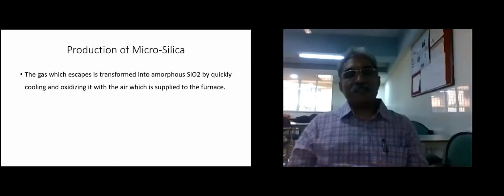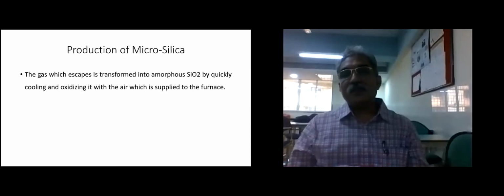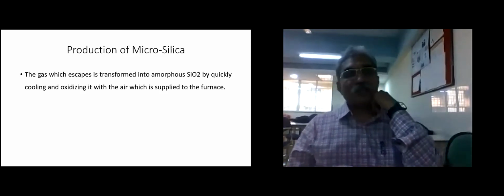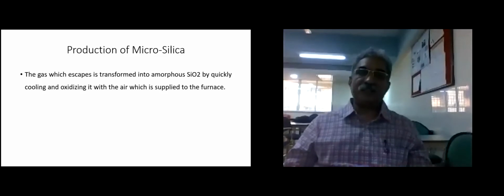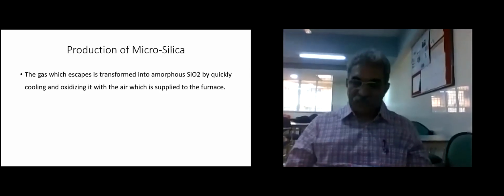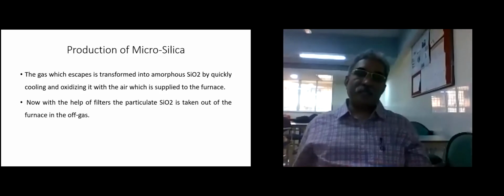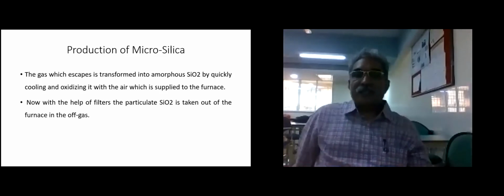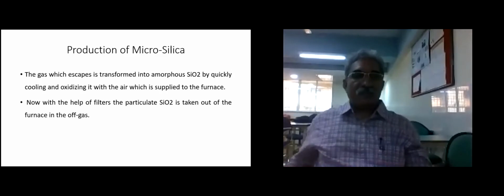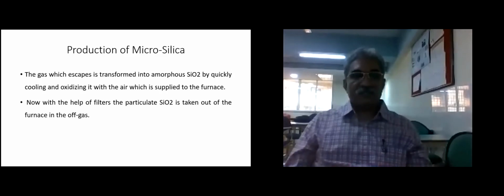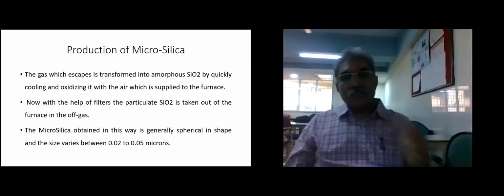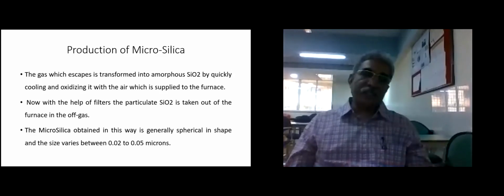The gas which escapes is transformed into amorphous SiO2 by quickly cooling and oxidizing it with the air which is supplied to the furnace. Now, with the help of filters, the particulate SiO2 is taken out of the furnace in the off gas. The microsilica obtained in this way is generally spherical in shape, and the size varies between 0.02 to 0.05 microns.